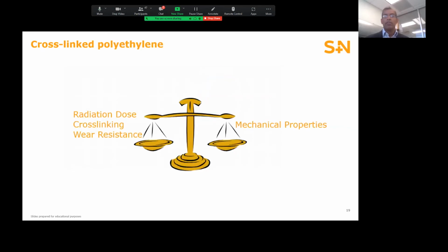So it's well known that cross-linking results in improved wear resistance for polyethylene. This process can be tailored somewhat. So if you want greater wear resistance, you can increase the radiation dose. And that'll result in a greater level of cross-linking and greater wear resistance. This relationship's not linear though, so there is a point of diminishing returns, at which point you're getting very little additional wear resistance with increasing irradiation.